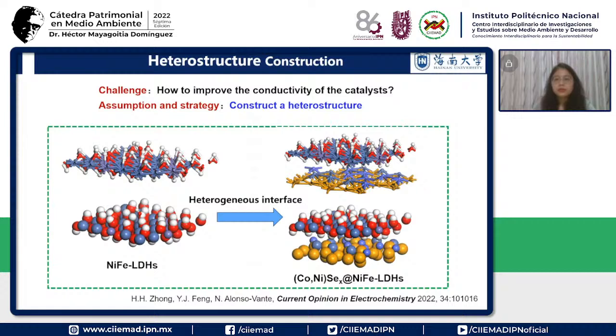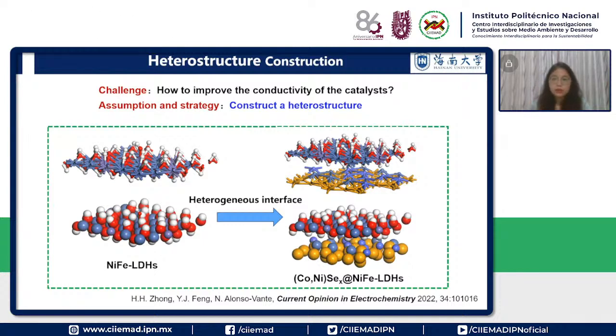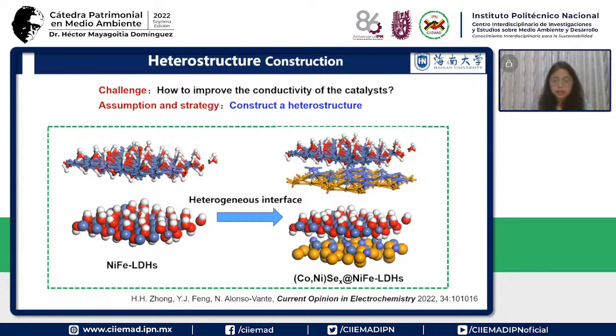And the next work, the last one I want to report, is we construct a heterostructure between LDH and cobalt nickel selenide. In the previous two works we got the cobalt nickel selenide or the cobalt nickel sulfide from the LDH. But now we want to make a heterostructure between these two materials, because we know the LDH is not so conductive for the reactions. So we want to build on the high conductivity of the selenides.